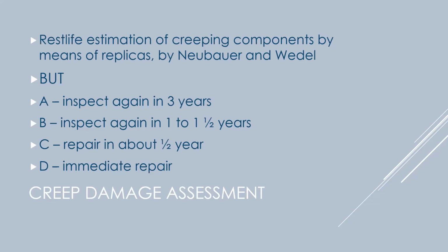And what they found is that when creep damage starts to occur, creep only occurs at high temperature, of course, the first thing that happens is you get these isolated voids occurring, and then they start aligning themselves. And then they become something called microcracks, because they're only about the size of a grain. And then they're macro cracks. At that point, you can pick them up with conventional NDE.